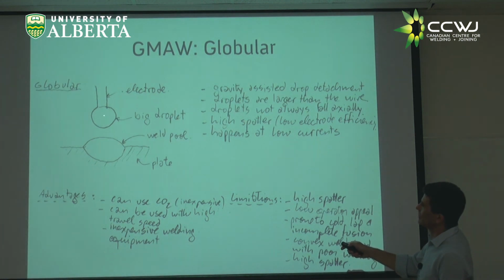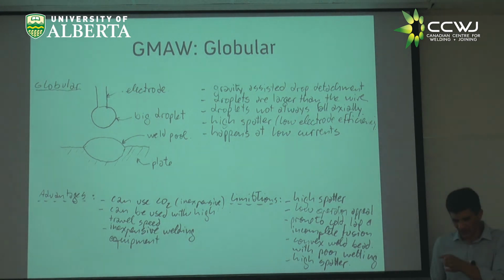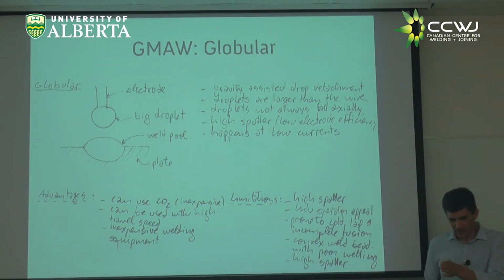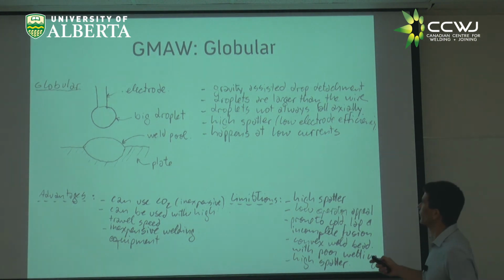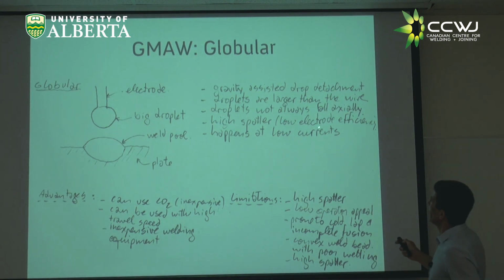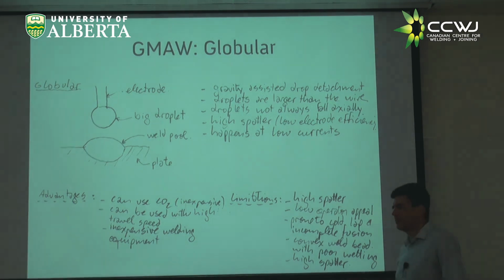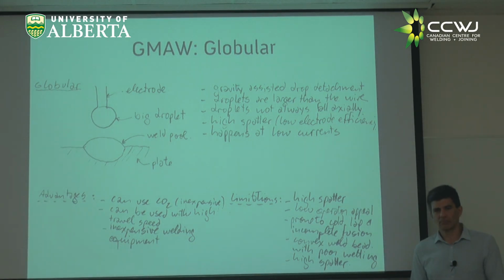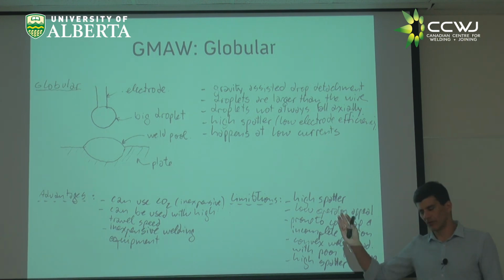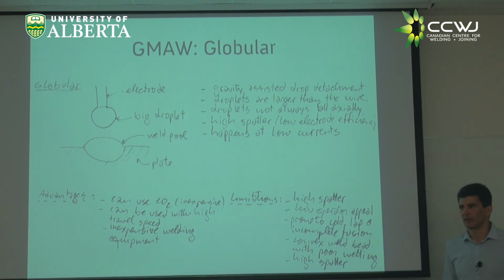And the droplets are relatively large. The droplets do not always fall straight, sometimes they go to the left or to the right, and this is a problem because a welder needs to put the metal right in a place and the droplet goes elsewhere. So you also have high spatter because sometimes the droplets fall out, happens at relatively low currents. For reasons nobody really understands. I don't. Nobody really can give you a straight answer. But if you use lots of CO2, you're going to have globular transfer, no matter what you do. You go to high currents, still globular transfer.